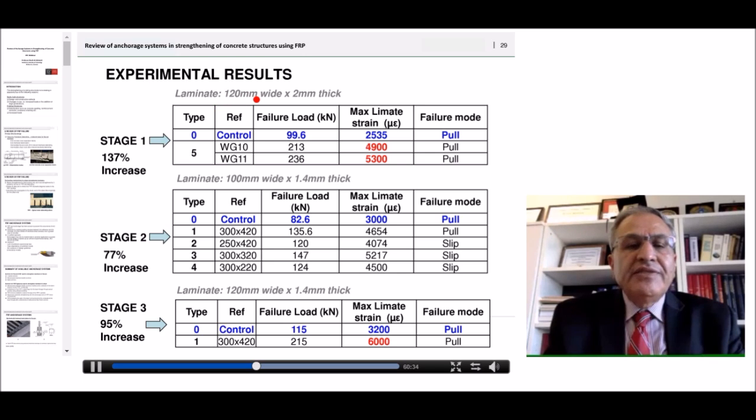we have got the control specimens, and have got two specimens that are used with bidirectional fabric. And what we found was that we got a failure of nearly 100 kilonewton, 99.6 in the control, whereas in the anchor specimens with bidirectional fabric, we get 236 kilonewton. In terms of the maximum strain capacity, it increased from